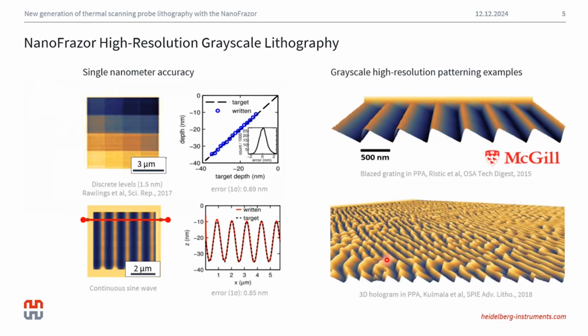So when it comes to grayscale lithography with the NanoFrazor, we can achieve single nanometer accuracy both for discrete type features like these steps that we see here, where each step is about 1.5 nanometer in depth differences. And also when it comes to continuous grayscale features, for example, sine waves, holograms, and also blazed gratings. So this grayscale lithography capability has proven itself to be very useful for photonics applications, and I'll come back to this later as well.